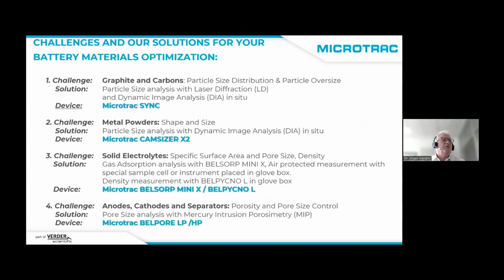So some of the challenges and our solutions for the battery materials optimization. We have here first one, graphite and carbons, particle size distribution, and the particle oversize. And this we did with the particle size analysis with a laser diffraction in combination with an image analysis in situ. So we measured this at the same time on the same material. And the device we used was Sync.